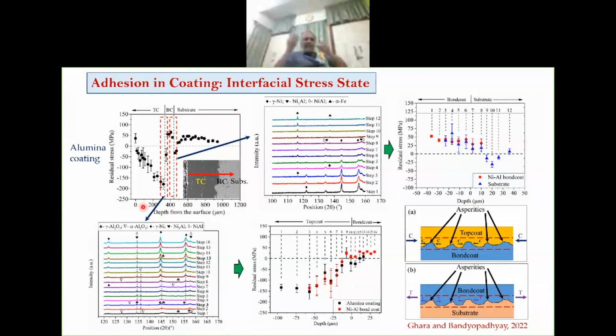Okay. So what is there at the top coat? Aluminium oxide. So near the top coat, we are supposed to get aluminium peaks in the X-ray diffraction. That's what we got. Then we gradually go in 5 to 7 microns. We go in slowly, and after some time we start getting nickel peaks from the nickel aluminide bond coat, and thereafter we do not see aluminium oxide peaks. We get only nickel peaks where we are well inside the bond coat. Okay, from top coat to bond coat. While we expose the layer, we measure the stress. What we see this time is that initially, somewhere here, it has a high negative stress.